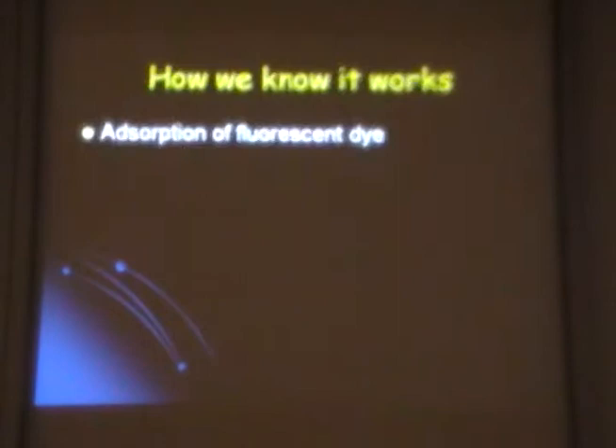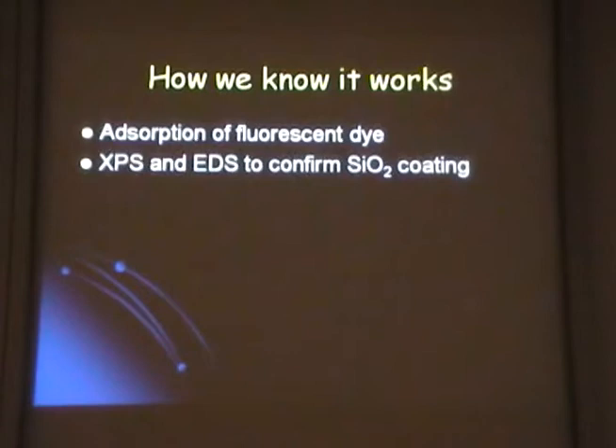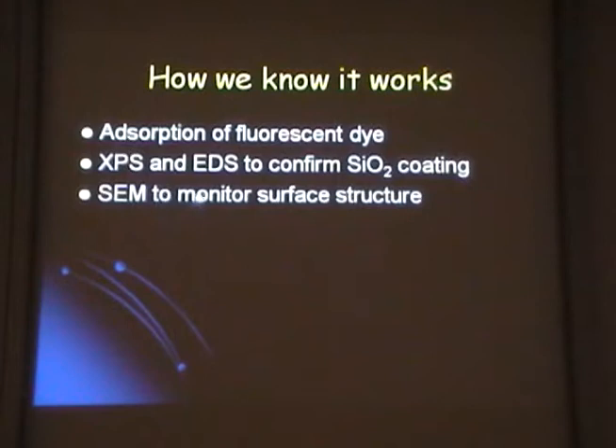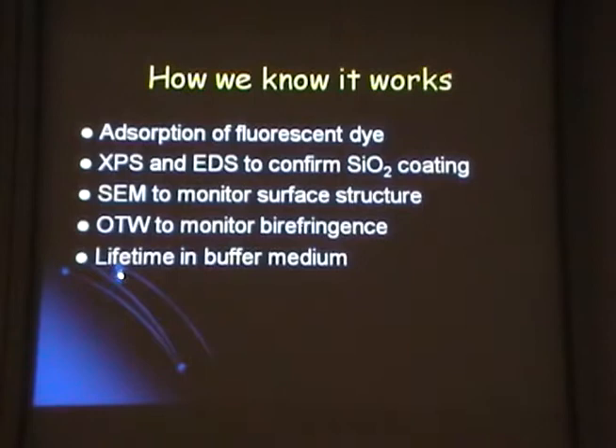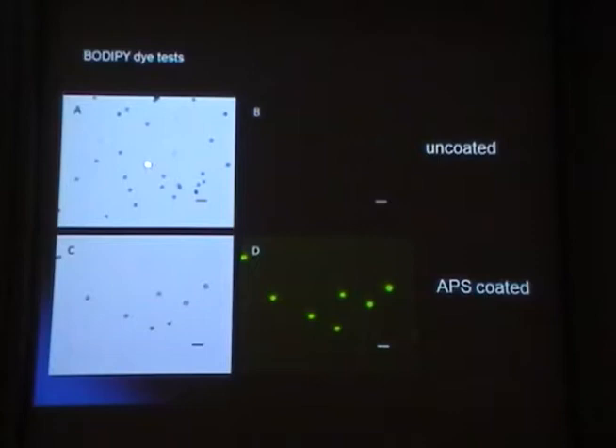Okay, so how do we know that this functionalization works? So I could adsorb a fluorescent dye. I can do XPS and EDS to confirm that I have a silicon dioxide coating on them. And I can use a scanning electron microscope to monitor the surface structure. And then put it into the buffer solution and see whether they melt. And in fact, when they are properly functionalized with all those layers which I showed you, they actually survive many hours in the solution. So here is the evidence of that. If I have uncoated vaterites and I look at them eventually in a fluorescence microscope, of course they don't fluoresce because there's no fluorescence attached to them.